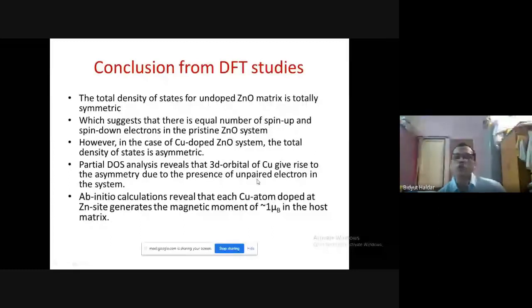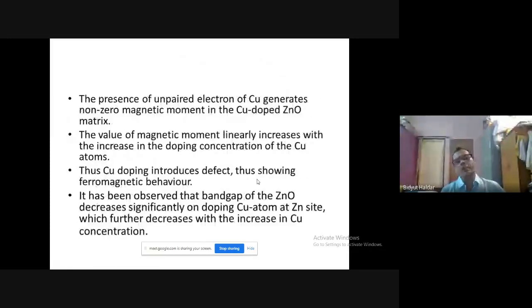However, in the case of the copper doped zinc oxide system, the total density of states is asymmetric, as we already saw. Partial density of states analysis reveals that the 3d orbital of copper gives rise to the asymmetry due to the presence of an unpaired electron in the system. Ab initio calculation reveals that each copper atom doped at a zinc site generates a magnetic moment of about 1 Bohr magneton in the host matrix. The presence of the unpaired electron of copper generates a non-zero magnetic moment in the copper doped zinc oxide matrix.